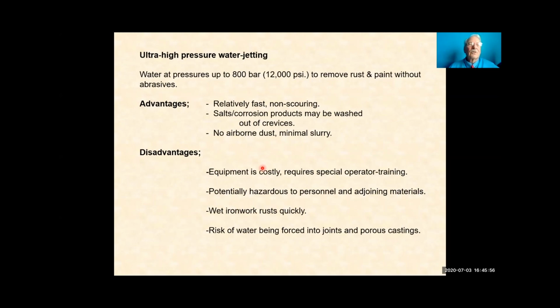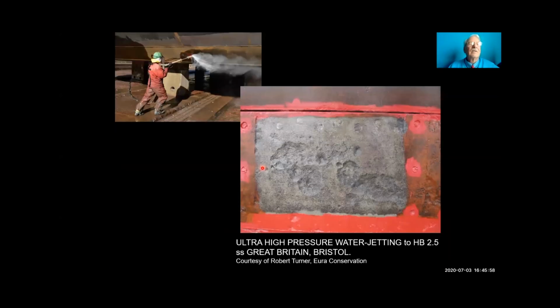And this is what it looks like. You look at the man on the top left here. He's actually having to lean forwards because the pressure is pushing him back. It's coming out there so fast onto the underside of this ship that he has to lean forwards and push against it. But it's very effective. This actually is the SS Great Britain that was cleaned in this way. It's a famous ship here in England from the 1840s. And it cleans the surface very well. But it is only suitable really for things like the size of a ship, sort of big areas. It's not very suitable for decorative metalwork, but a good process nevertheless.